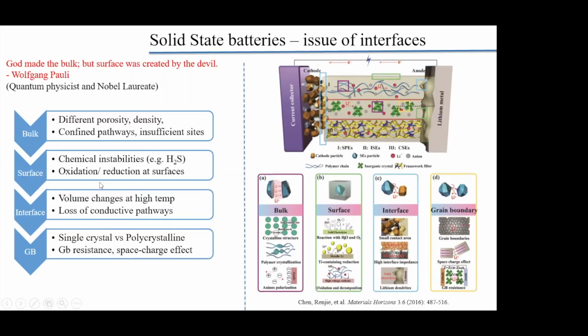And then at the interface, many of these smaller interfaces between the particles, between the electrolyte and the electrode, you need to make sure there are no drastic volume changes at high temperature. As the cell starts working at high temperature, it should not lose conductive pathways. So if, because of high temperature, one of them expands rapidly and loses contact with the other interface, then you lose this pathway, and lithium cannot go to the other side because of excessive volume change. And then there's something, so, like we spoke about bulk, at the bulk you have porosity.